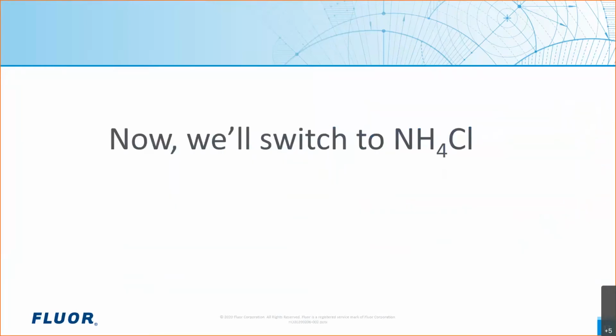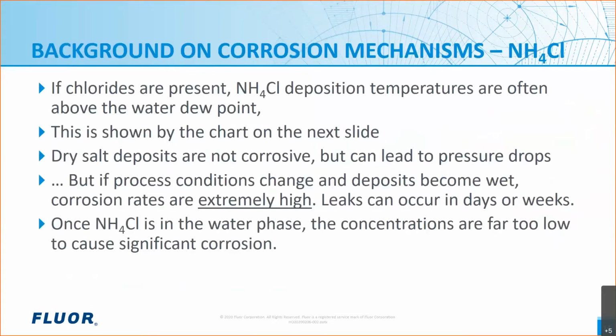Okay, so now we're going to switch to talking about the background on ammonium chloride corrosion in reactor effluent systems. If chlorides are present in the reactor effluent, one of the risks is that ammonium chloride deposition temperatures are often high above the water dew point. And when we say chlorides are present, even 3 ppm of chlorides can be enough to start getting us into trouble. We show a deposition chart on the next slide.